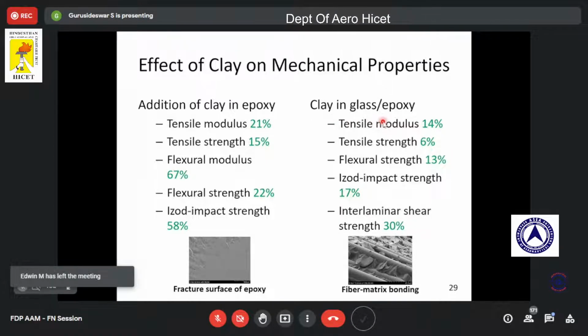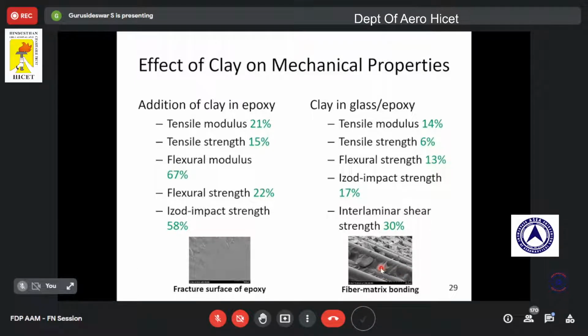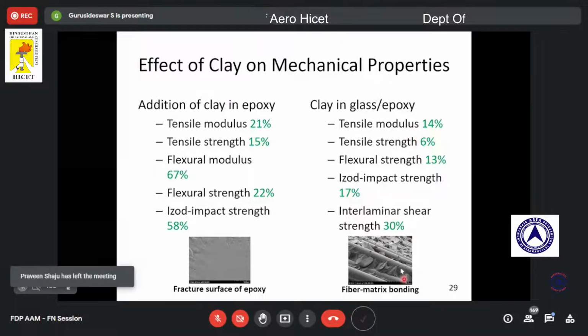Again, this is the photograph of the fiber reinforced composite. You can see that by addition of clay in the matrix, there is very good bonding between the matrix and the fiber. This bonding leads to better performance in mechanical properties. So this is how we understand the effect of clay in a general composite, the glass epoxy composite.